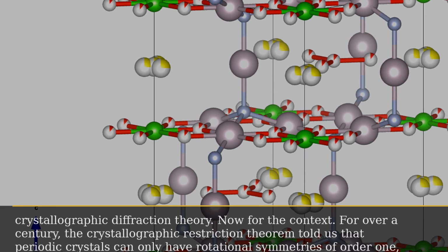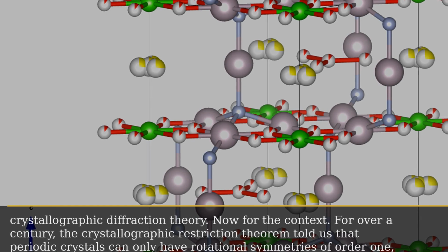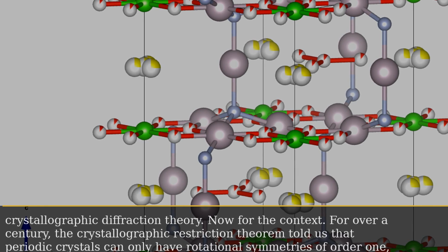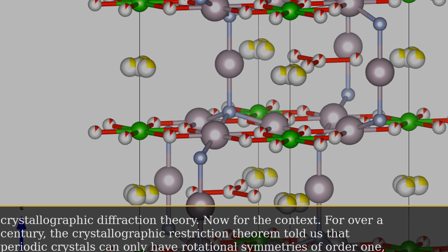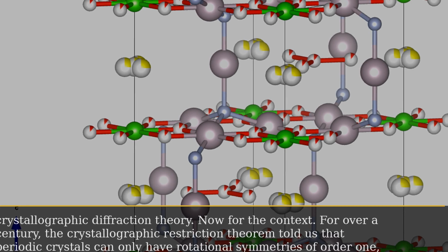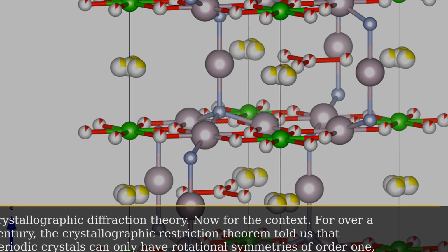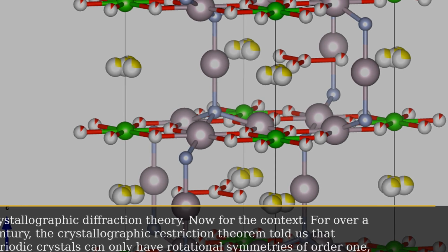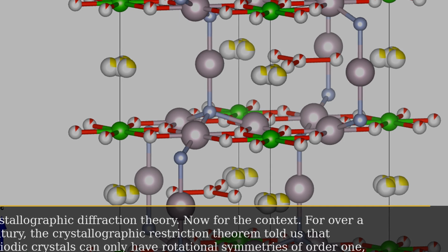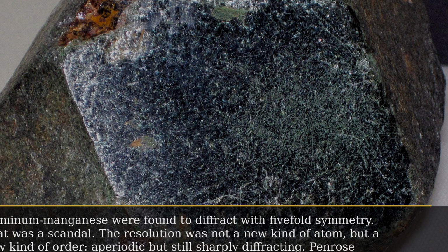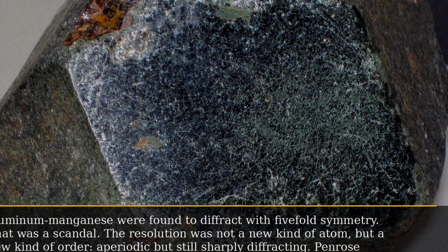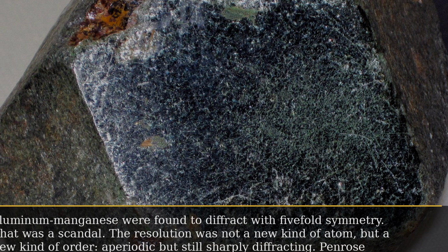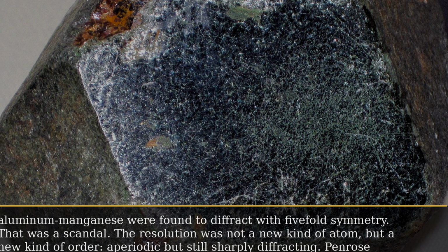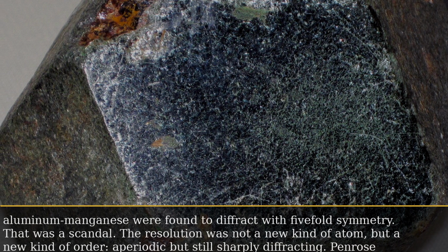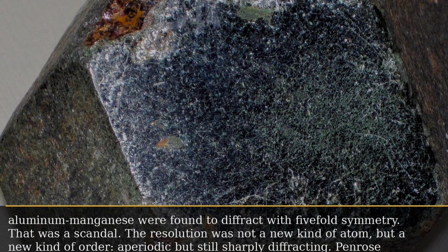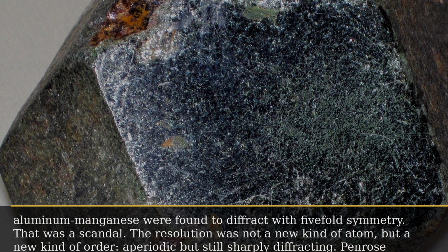Now for the context. For over a century, the crystallographic restriction theorem told us that periodic crystals can only have rotational symmetries of order 1, 2, 3, 4, or 6. Fivefold symmetry was forbidden. Then, in the 1980s, real alloys like aluminum manganese were found to diffract with fivefold symmetry. That was a scandal. The resolution was not a new kind of atom, but a new kind of order, aperiodic but still sharply diffracting. Penrose tiling is the purest mathematical model of that order.